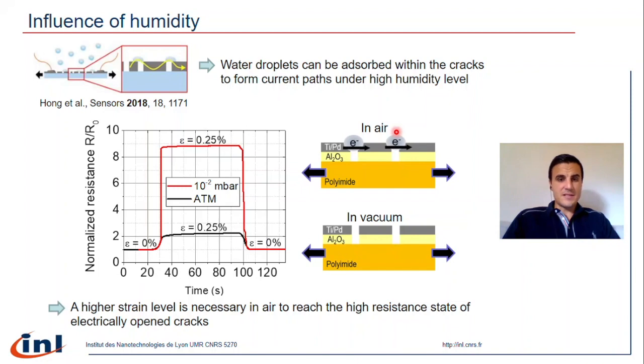To verify this, we have placed a non-encapsulated flexible transducer in a cryogenic probe station. The idea was to submit this transducer to a 0.25% strain load in air and in vacuum, and to compare the resistance variation. The results of this experiment are presented on this graph.